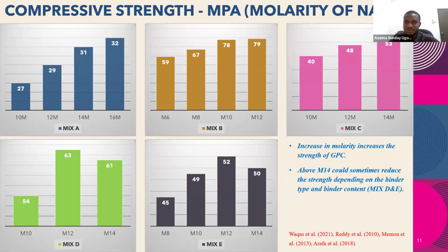Then the molarity of the sodium hydroxide. If you look at all the mixes, the first mix, for mix A, mix B, and mix C, I know I said increase in molarity increases the strength of your GPC because the sodium hydroxide content, if it's more concentrated, enables a higher reaction with your binders and a speedy reaction. So you're most likely to get a higher strength concrete with a higher geopolymerization. However, if you go too high, in some cases, when you go past 14 molarity, the strength may reduce.